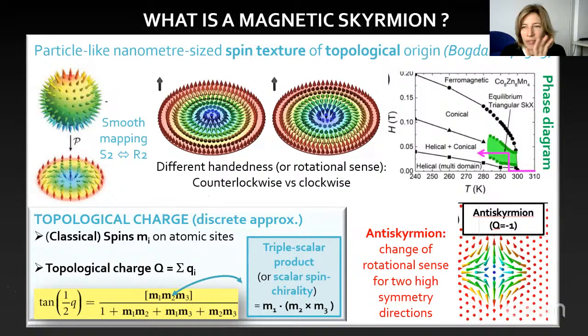And yeah, phase diagram of many systems showing Skyrmion is actually complex and common. Most of them have some helical order. They start from something which is already a bit frustrated, like a helical spin system, or spiral, or conical. And then if you apply a magnetic field, you get into a region in which you have Skyrmion.